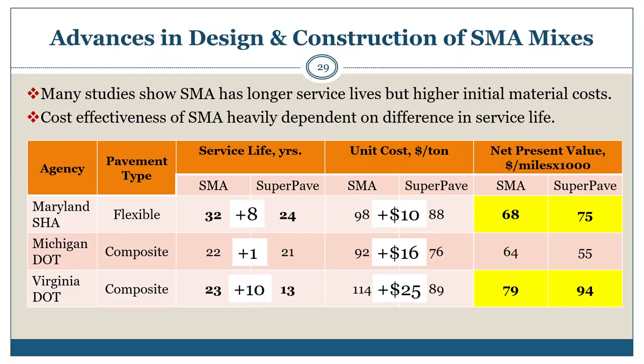The average unit cost difference between SMA and dense graded mixes is shown on the average unit cost. In Maryland, there's a $10 additional cost per ton of mix for SMA compared to Superpave. Michigan has a $16 added cost per ton for the SMA mixtures, while Virginia has an added cost of $25 per ton on the average for SMA mixtures in comparison to the Superpave mixes.